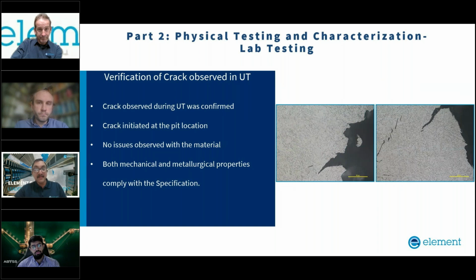We have done further analysis of the area where we found a through-thickness crack during UT inspection. When we cut and polished this section, we saw that a crack has generated at the pit location due to the environmental condition of the asset. Once again, there was no problem with material degradation. Whatever corrosion happened is due to the pit, and this has also generated a crack inside the material.